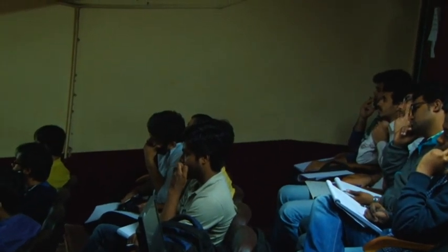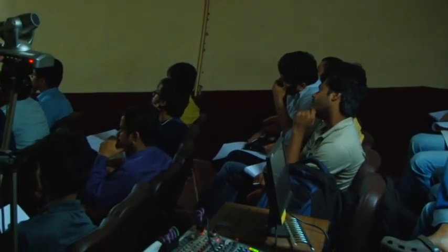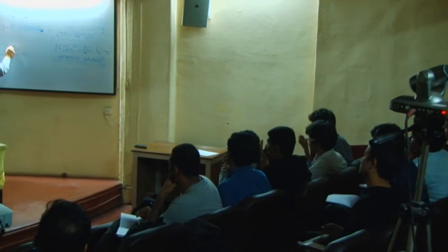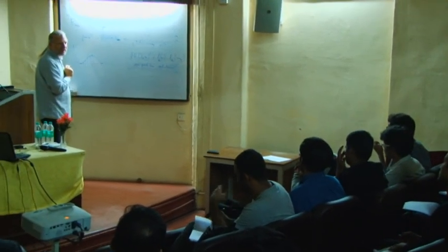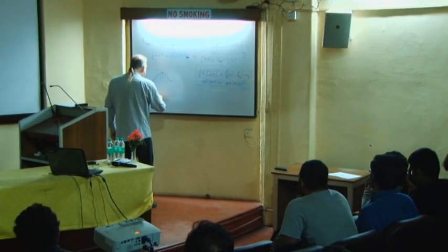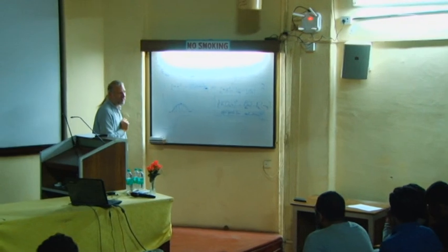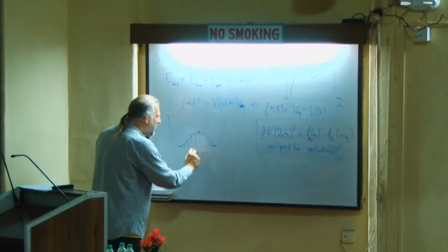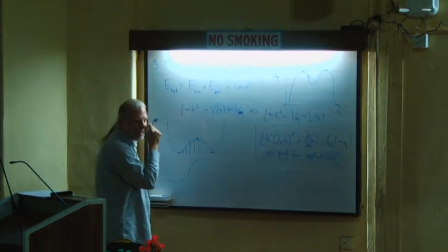Well, you see, this is equal to this energy difference. So I can say the gradient of m that I find is proportional to this difference. Which means that from this shape I can immediately read off that the gradient will be steepest in the center of the interface. So no matter what's the detailed shape of that double well potential, the interface will always be of this type, with the steepest gradient in the middle and going smoothly out of the equilibrium thing.